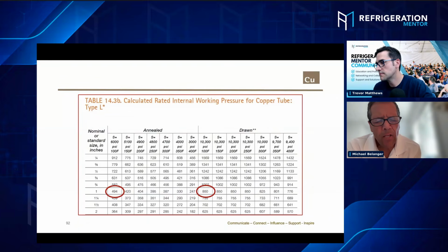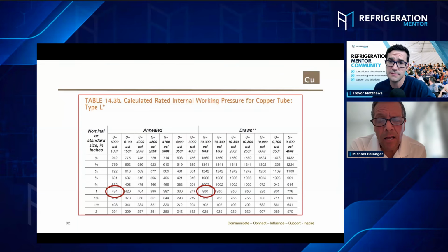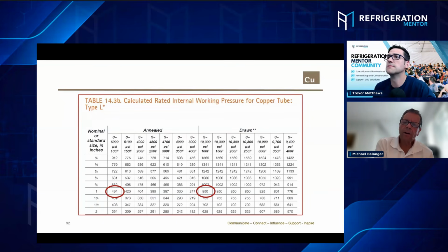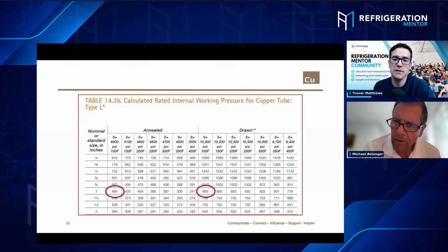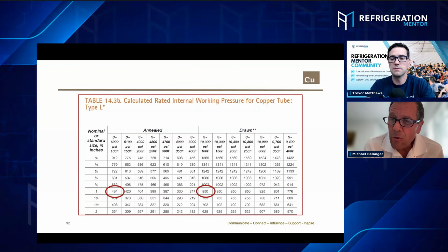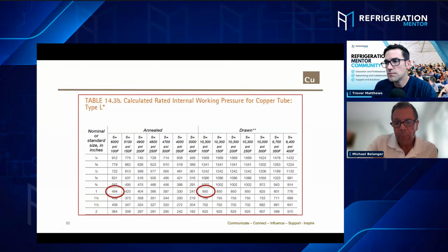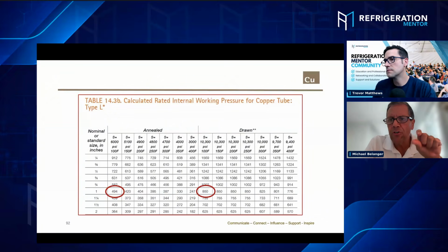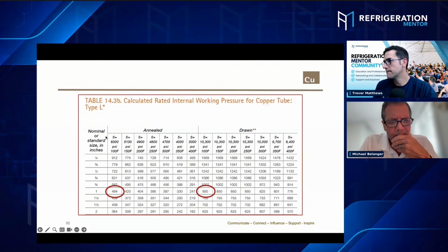Well, when you say 700 psi, you're talking about a joint rating? Yeah, annealing, the pipe being. Okay. You know what, Trevor? I prefer to defer to the Copper Tube Handbook. You know what I mean? For example, with a copper press system on refrigeration where the tube is not annealed, that's 700 psi, but limited on the application in terms of temperature, vibration, those kind of things. So I prefer to use the Copper Tube Handbook as the manual that I would prescribe. You're talking even with annealed 1-inch type L, 500 psi. However, it is dropped down from drawn at 850.